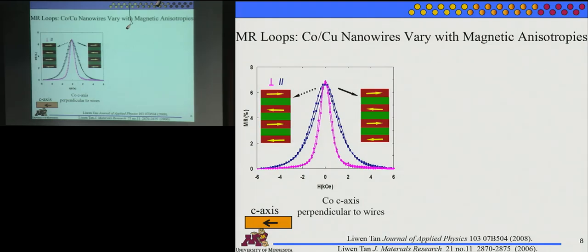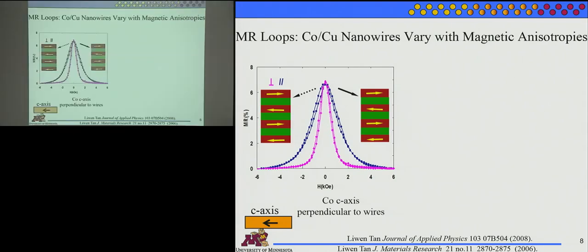I can see now the VSM loop of these actually looks the same because I'm measuring all of the layers in every single wire in the sample when I use a VSM, where here I'm measuring properties that are specific to along the wire.